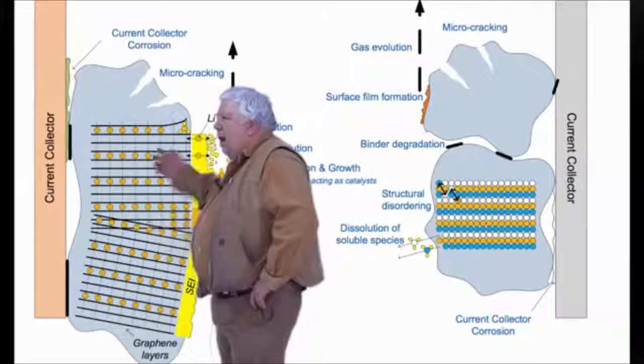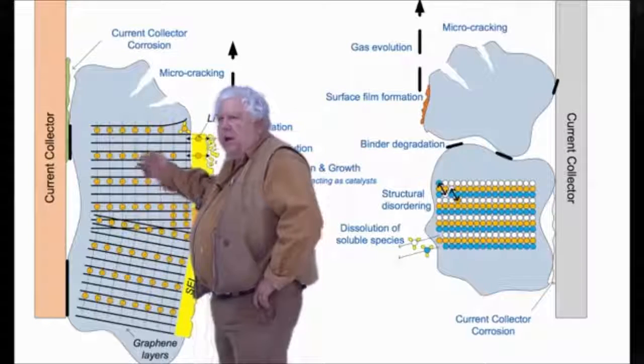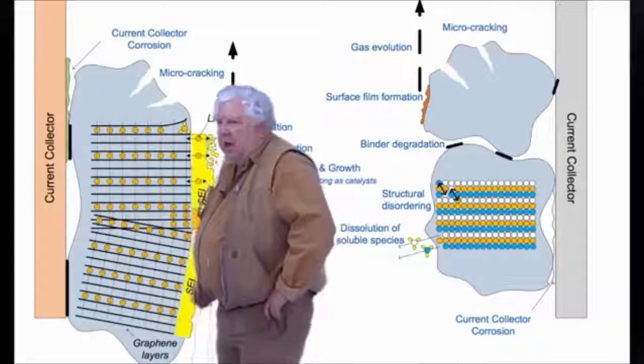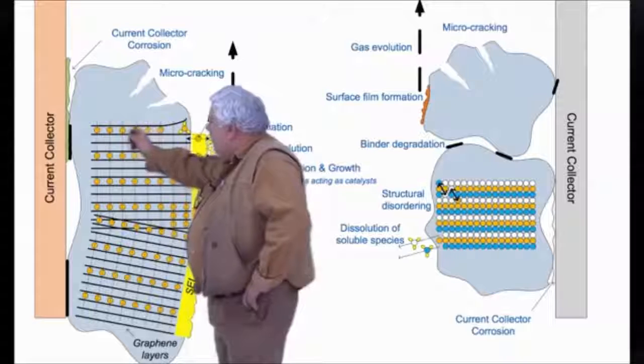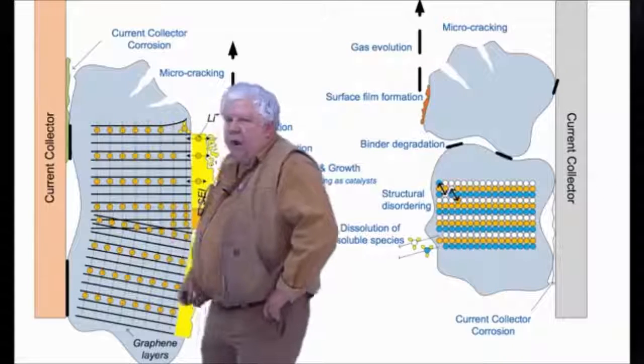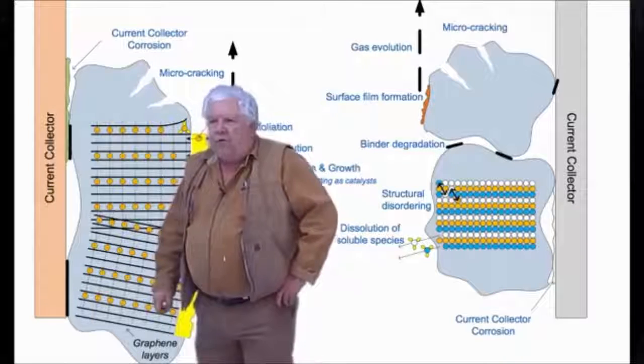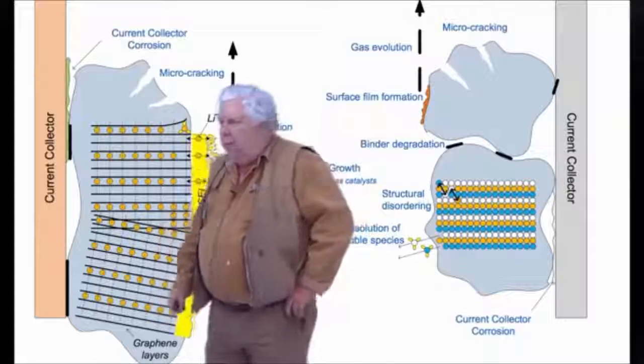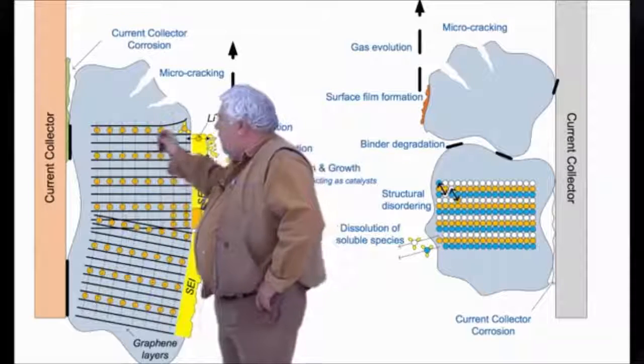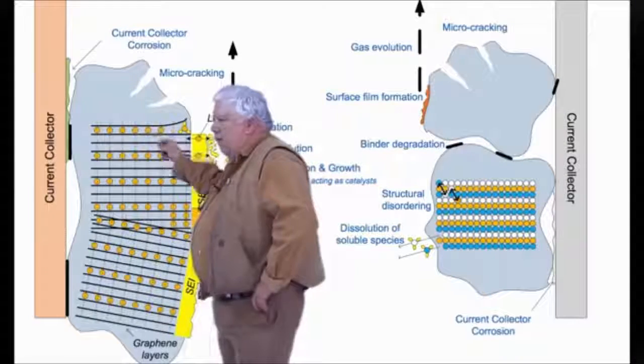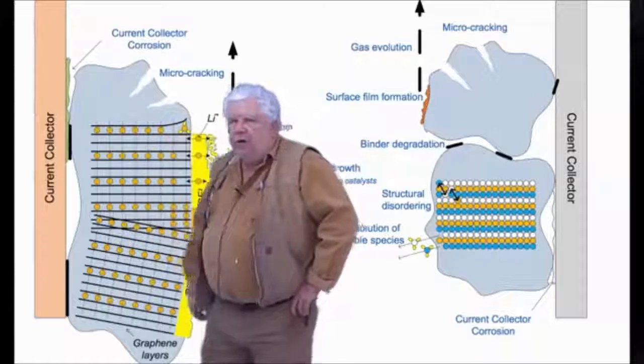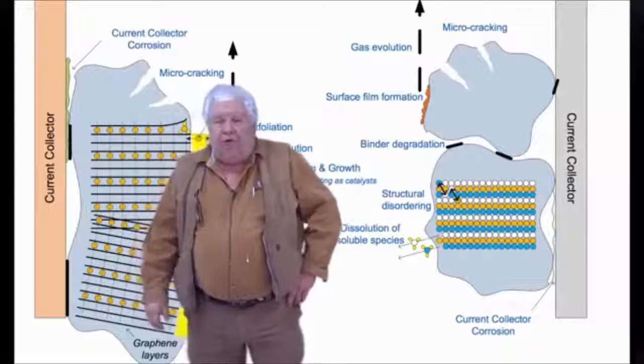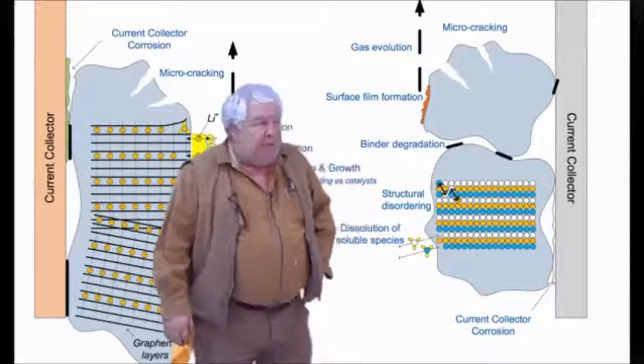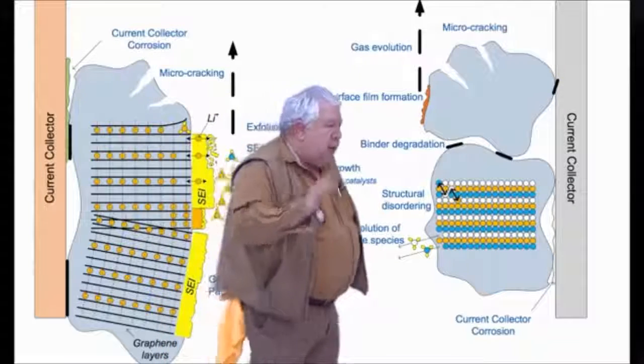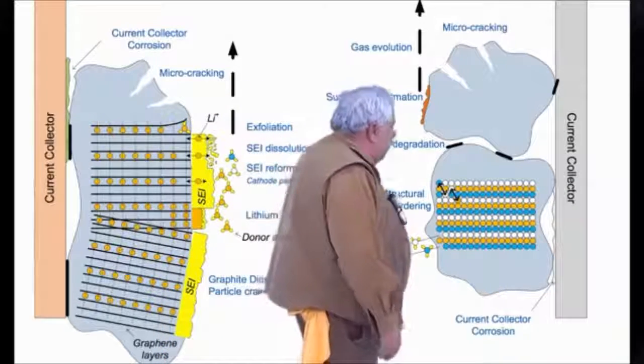And so we have kind of a wound in our SEI layer that is a function of the size of that lithium crystal, and it tends to grow outwards as a dendrite. Some describe it as moss. More commonly, you'll hear it termed a dendrite, a little needle that comes out and starts poking into our separator. If it goes through the separator, we short the cell and we have a fire. But we don't have to do that to get a fire.